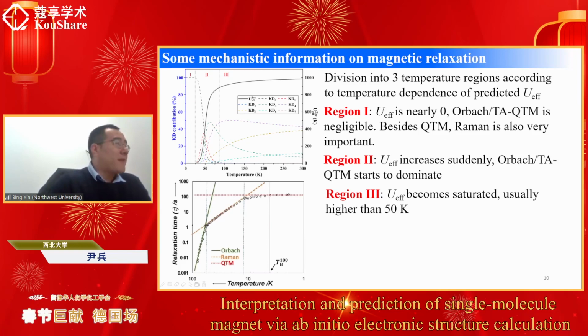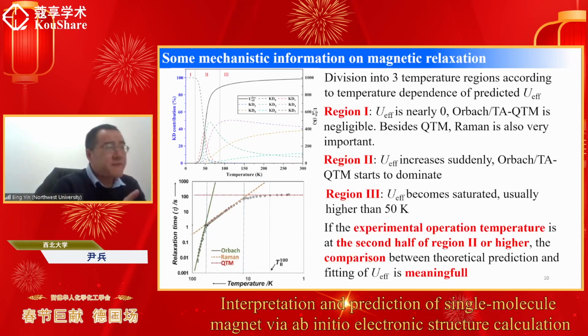In region 2, we can find that the energy barrier increases suddenly. That means the thermally activated part starts to dominate, or start to take control. And in the final region 3, the energy barrier becomes a saturation value, which means the thermally activated part is the dominant one. But region 3 usually starts at temperatures higher than 50 Kelvin. So we think if the experimental operation temperature is in the second half of region 2 or higher, then the comparison between theoretical prediction and the experimental fitting of the energy barrier is meaningful.